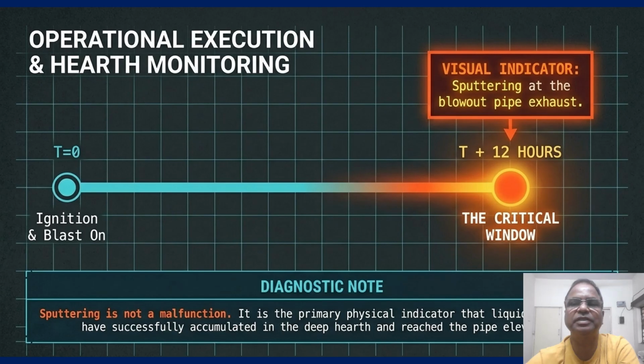Sputtering is not a malfunction. When you see the blowout pipe exhaust start to sputter, it's your primary physical indicator that slag and iron have successfully accumulated in the deep hearth and reached the pipe's elevation. This is the eureka moment of the blow-in, which tells us the hearth is alive and receiving liquids.